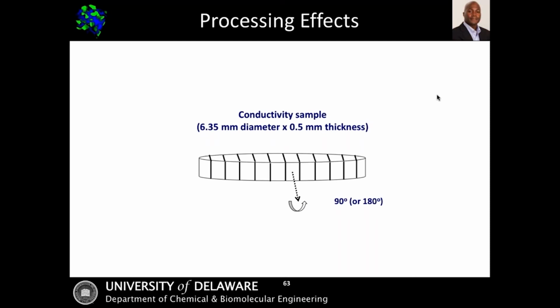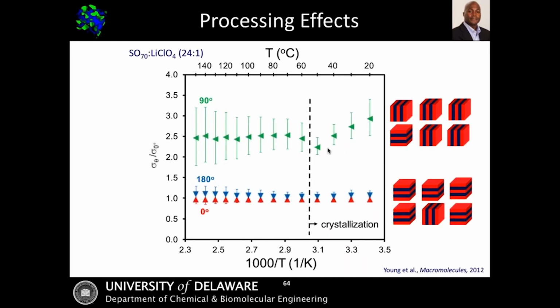In this particular case, one of my students did a very tedious experiment where we made a polymer disc, and he sliced it into a bunch of sections as shown here. We did a sandwich cell geometry to look at the conductivity, and then he took those slices, rotated them 90 degrees, resealed the sample cell, and measured the conductivity again. Then he rotated the samples 90 degrees again, to 180, and remeasured the conductivity. So why did we do that, and what did we see?